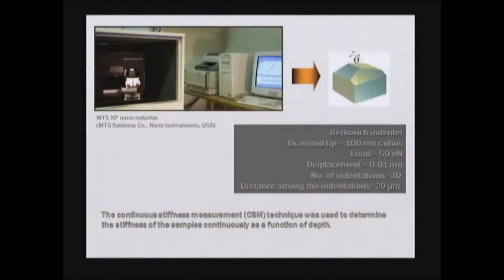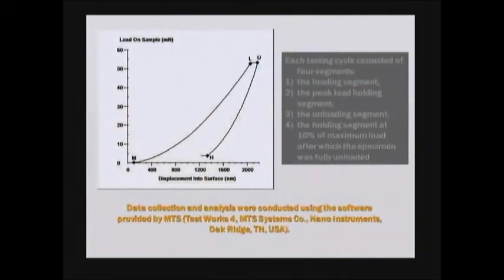This is the specific specifications of the nano indenter: diamond tip, 100 nanometer radius, and the load is 50 nanonewtons. So that's why we're talking about nano indentation. So the loads are very, very small. And we used the continuous stiffness measurement technique to determine the stiffness of the samples. This is the trace that you get from nano indentation. So you get the loading segment, then you have the peak holding time, and then the unloading. And from that trace, you were able to calculate your stiffness, which is the Young's modulus of the material.